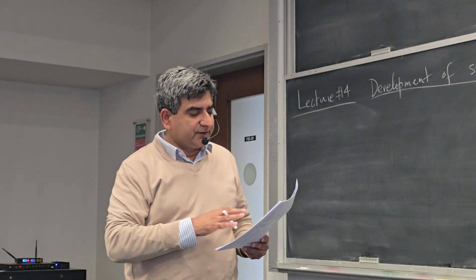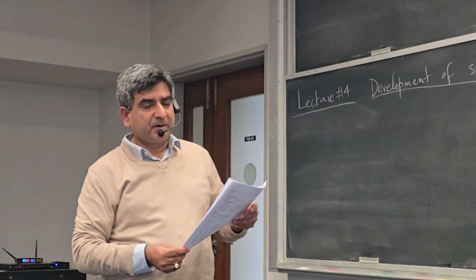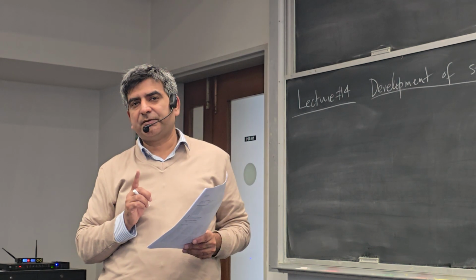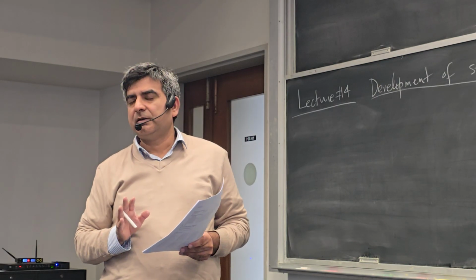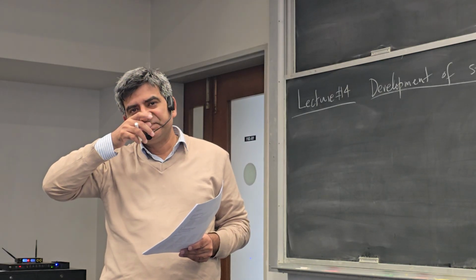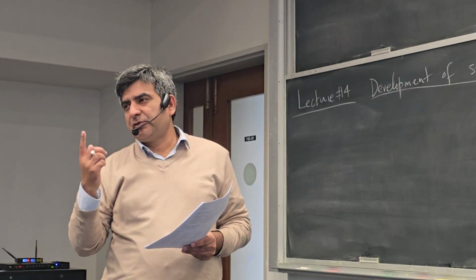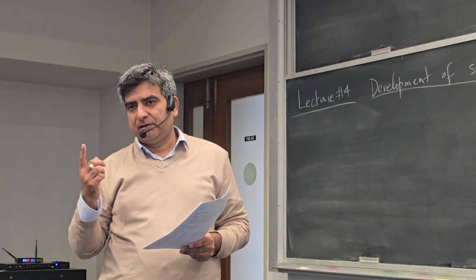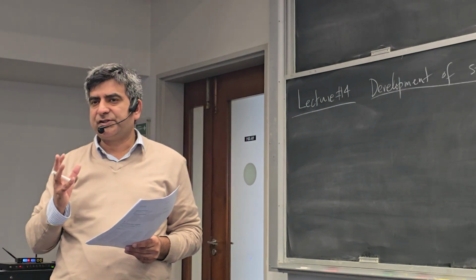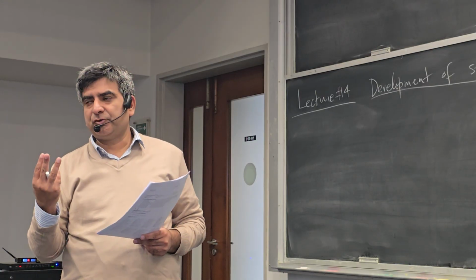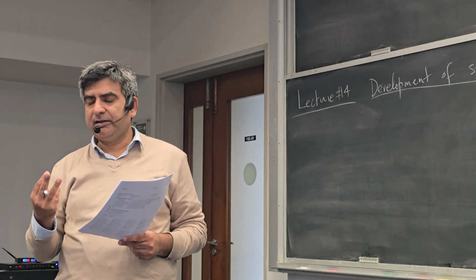Now in the last column you can see space groups. For example, if you look at triclinic, point group number 1, there's one space group associated with it, which is P1. And I'll explain what these space groups mean. Okay? With the point group 1 bar, there is only one space group associated, P1 bar. I'll explain what it means. With monoclinic, the point group 2 or C2, there are 3 space groups associated: P2, P21, and C2.